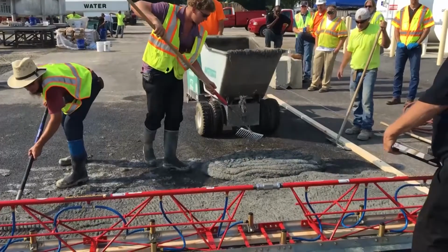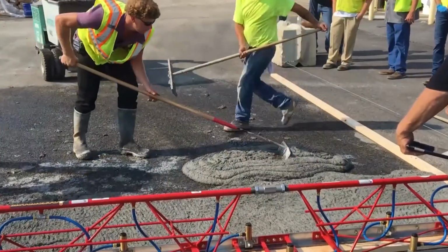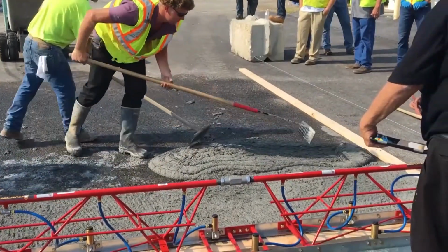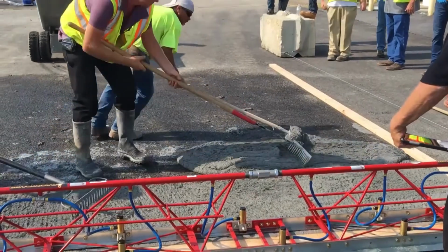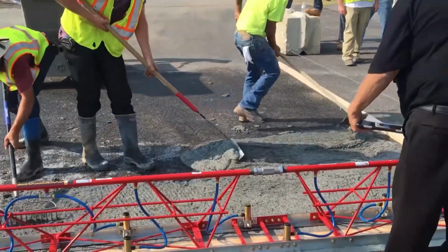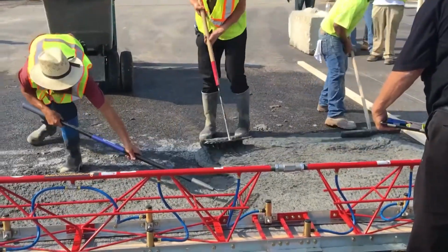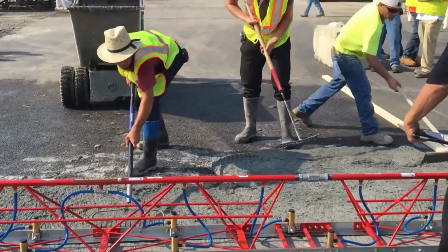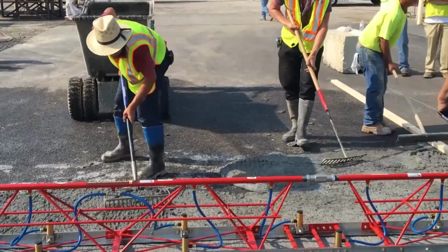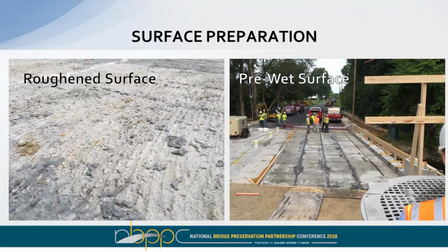So you can see it kind of flows out fairly fluidly, and then the second it starts to spread, it really kind of stabilizes on itself. And then we just have guys with some rakes, shovels, moving the material around in front of that screed. Pretty easy to do, quite frankly, but you need to have enough folks to be out there to do it properly. They had a roughened surface to pour against. They pre-wetted that surface before they placed the material.